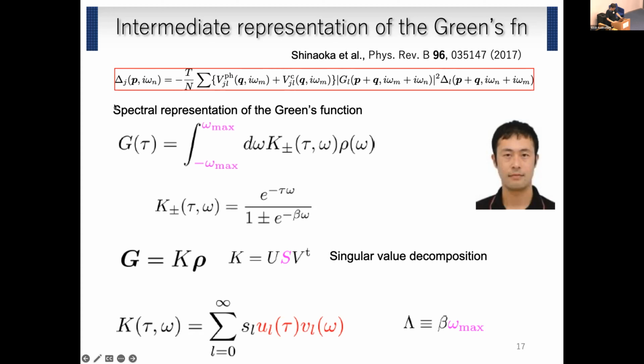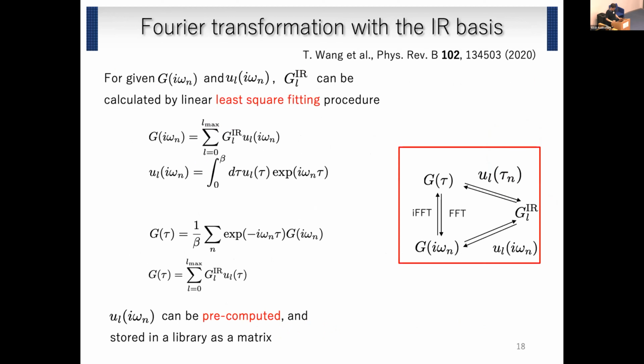And if we use this, then actually we can solve this Eliashberg equation, because if we look at this equation, we see that it is a convolution of interaction and Green's function. So if we do a Fourier transform and go to tau space, then we can calculate the right-hand side of this equation. So the point is how to do a Fourier transform efficiently. And if we use the intermediate representation, we can do that very efficiently, because G(i omega) or G(tau) can be expanded in terms of this U. And this U can be pre-computed and stored in the library.